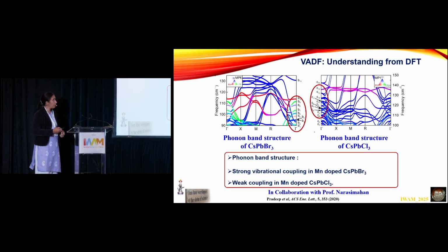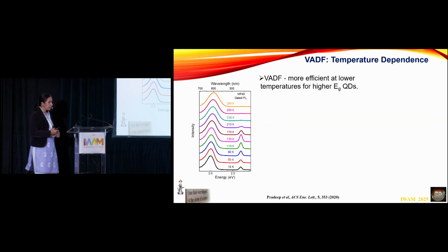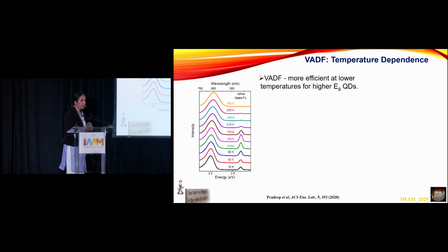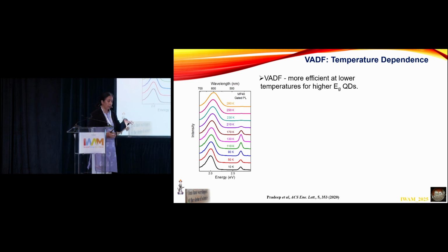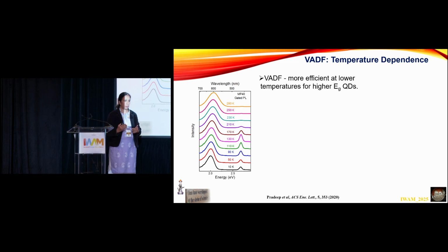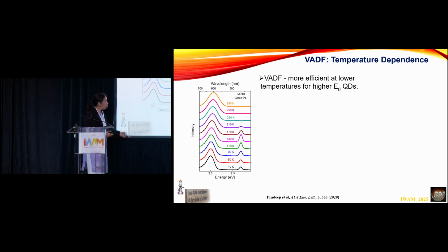So experimentally, can we observe this? If I need to prove that there is a phonon interaction, what I need to do is to show that it's actually stronger at lower temperatures, unlike TADF, which is thermally assisted and becomes stronger at higher temperatures. This should become stronger at lower temperatures.